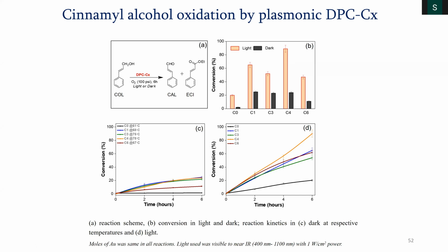Then the hypothesis was that when you expose the black gold with a light, you excite the electron in the Fermi level to higher state, energetic electrons or hot electrons, and these hot electrons then get transferred to the oxygen. Oxygen is your oxidizing agent, and you dissociate the oxygen. And now you have a dissociated oxygen, which is highly reactive, and therefore you get a better kinetics of the alcohol oxidation.